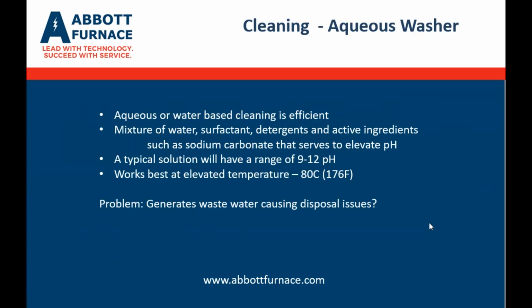Another method to clean the parts is just a simple aqueous washing machine. Using water-based cleaning is very efficient. It works very well, using a mixture of water, surfactant, and detergents, to really elevate the pH, which is the main goal. A typical solution would have a range of 9 to 12 pH levels. And the aqueous washer does work better at slightly elevated temperatures.